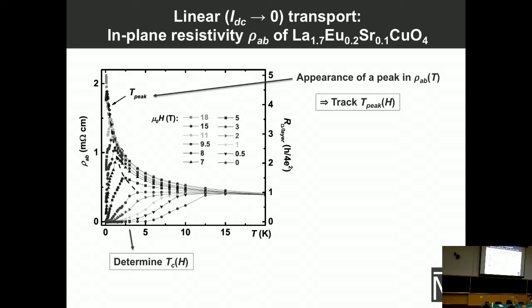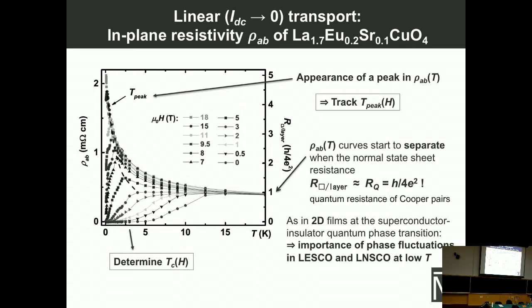Before I continue, I'd just like to point out this really striking fact that these different curves start to split into two families, those that become superconducting and the others that do not want to be superconducting, when the normal state sheet resistance is essentially the same as the quantum resistance of Cooper pairs, h/4e². This is what you expect in 2D films near the superconductor-insulator transition, driven by the loss of phase coherence, where Cooper pairs persist on the insulating side.